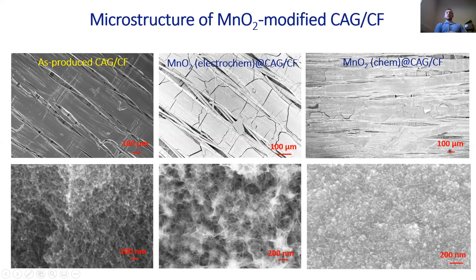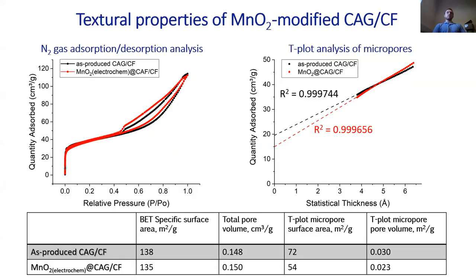In the case of electrochemically deposited material, we have long nanowires interconnected into large mesopores. While in the case of the manganese oxide deposited chemically, we have more uniform coverage with fewer cracks appearing on the surface, which is the result of the stress shrinkage appearing during drying. And the microstructure consists of small nanoflakes forming a smaller pore size compared to electrochemically deposited material.